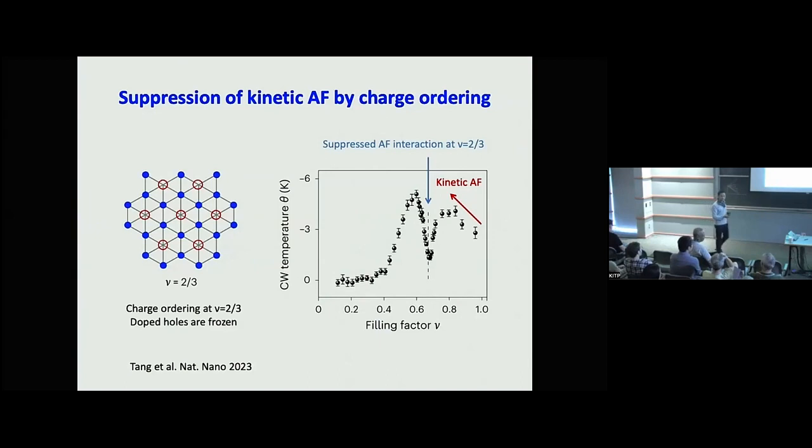Maybe I can try to answer it. Let me give you another way of thinking about it. Let's say we don't vary the temperature of the system. We go to the low temperature limit and measure the saturation magnetic field as a function of the filling factor, and the saturation magnetic field does go up with increasing doping. In this audience, which heavily studies insulating antiferromagnets, it's common to think that as you lower the temperature below some order 1 fraction of the Curie-Weiss temperature, it magnetically orders, and that's not going on here, as far as we can tell. That tells you that the physics is somewhat different, right? But it's interesting.